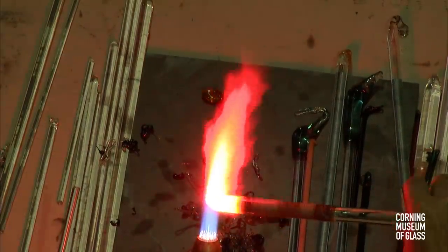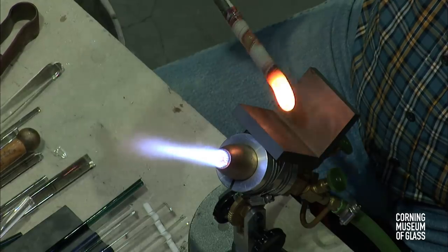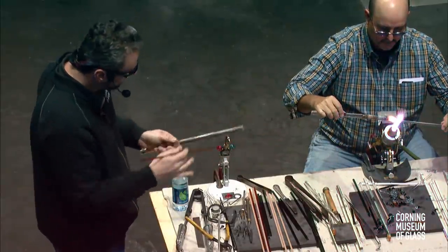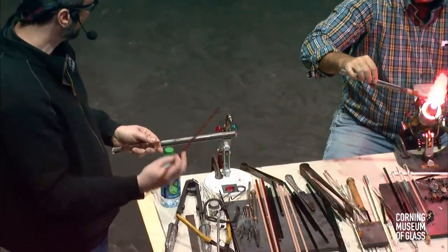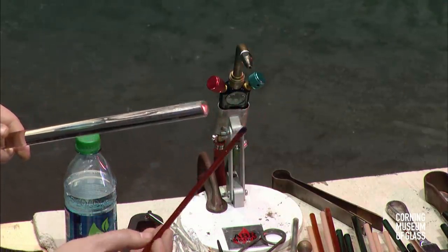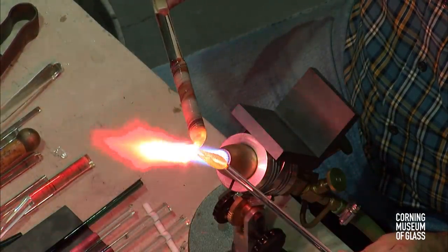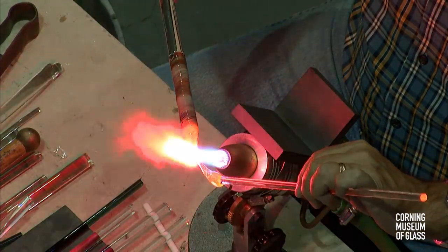Okay, how did David mix the color on these glass rods? Really, all he did this morning for his prep work was to take a rod of colored glass, heat up a thicker rod of clear glass, and draw stripes of that colored glass onto the clear. That built up a larger volume for him to work with. This particular color in my hand is very densely colored with silver and germanium. This combination of colorants with this density will give a broad range of colors, from an orangey amber to a really dense transparent purple. You'll get some bluish gray tones as well. So he's getting a whole variety of color effects from this one type of color rod. All of his prep was a matter of striping thinner color rods onto a big, thick rod of clear.